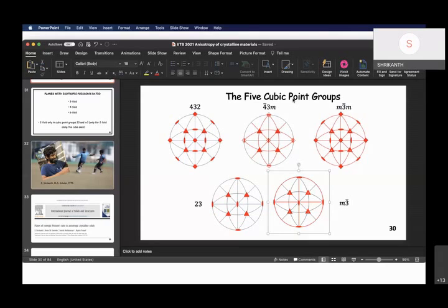For specific cases, I've identified all the solutions. Cubic is easy to work with, and cubic will only have these high symmetry directions. We can show that there are no compliance-dependent loading directions, that it is isotropic. Tetragonal is also easy to work with. I was also able to derive expressions for each of the loading directions which are isotropic.